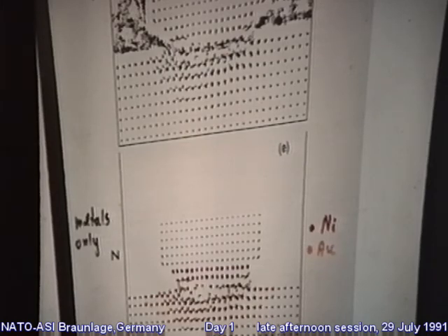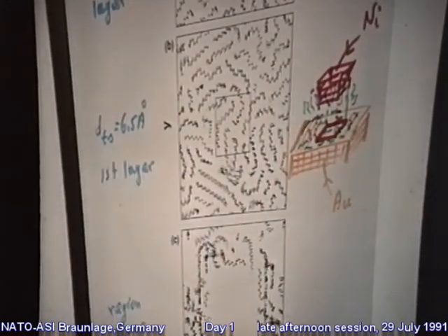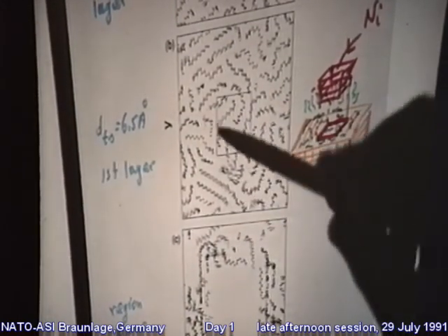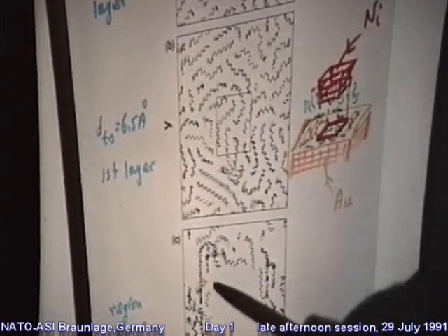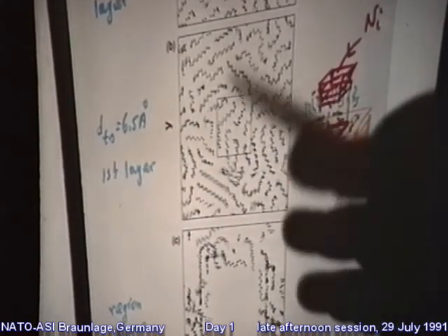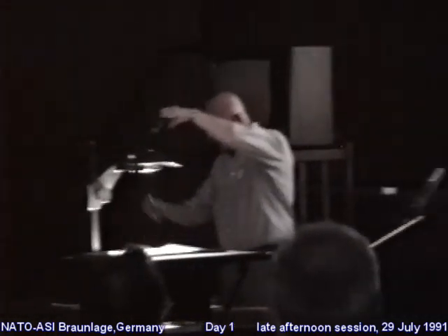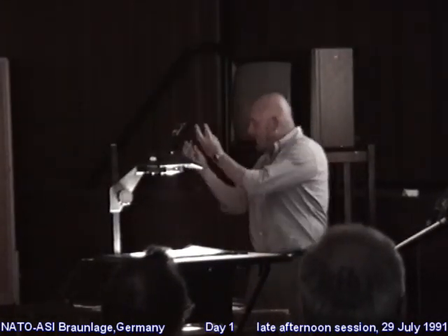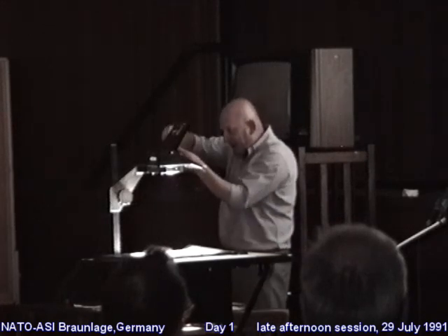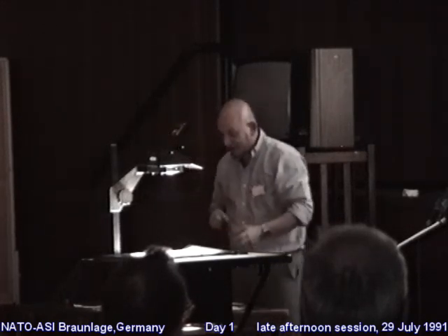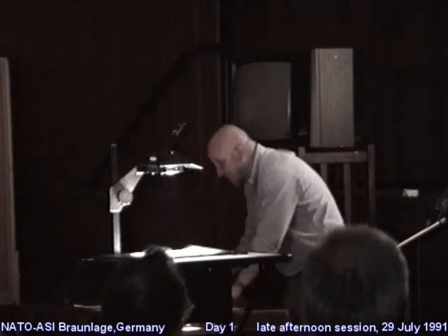As a matter of fact, if you look down on this thing, I will not go into detail. This is some of what you find. This is a picture here, for example, what happens right under the tip. This is the whole of all the molecules above. So you see the first layer, you see ordering under the tip. So I did expect something else. I didn't think that it will actually freeze and it will never jump to contact, but it does jump, although there are some alkanes. So in other words, metal atoms do adhere to one another, but they're interlaced with some alkyl molecules. Very interesting. Let me almost close here.